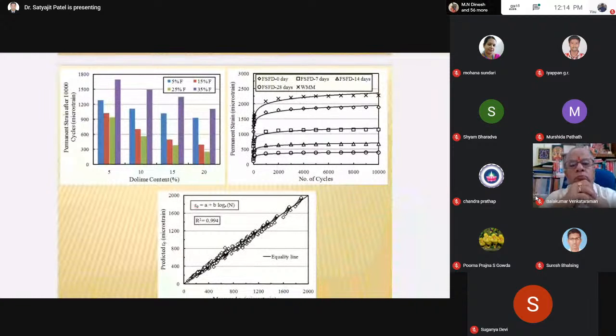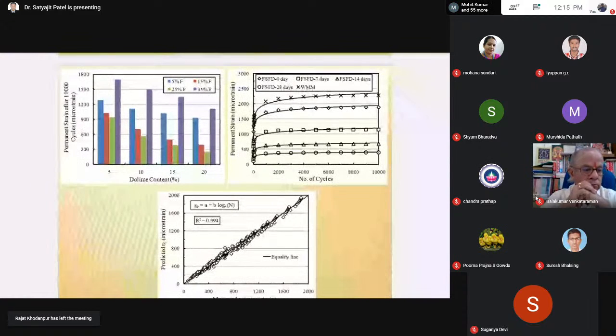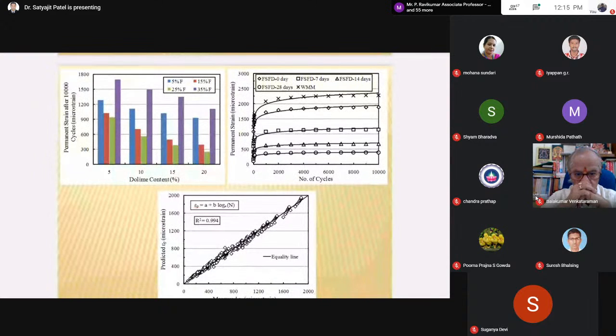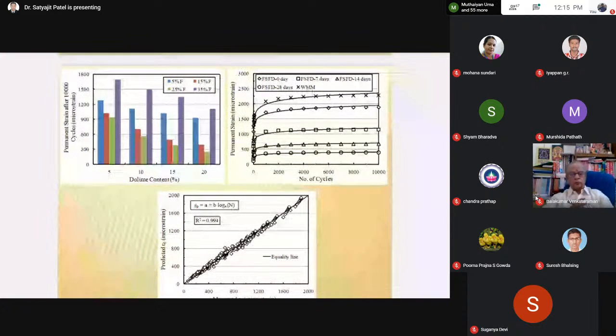Permanent strain can be obtained up to 10,000 loading cycles. I applied up to 10,000 loading cycles to study the permanent strain behavior of different materials. If you see here, the WMM has the highest permanent strain, so WMM has the highest rutting potential. The waste material, being a cemented material, has quite low rutting potential compared to WMM.